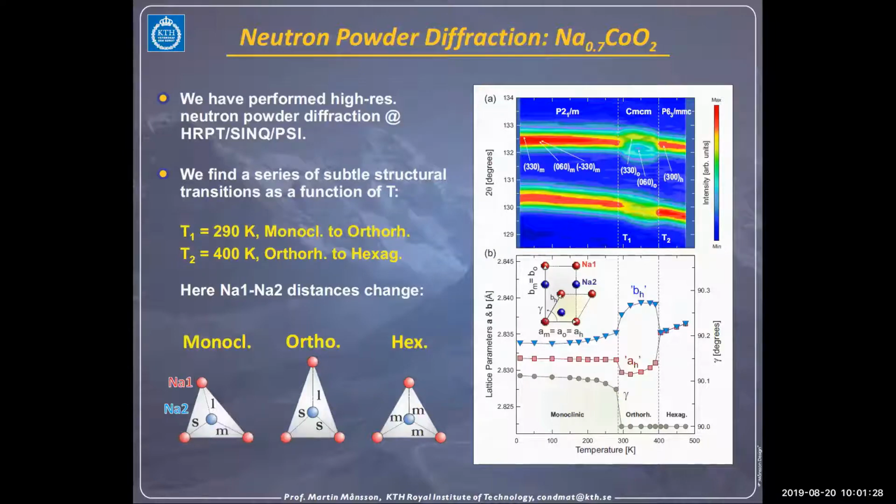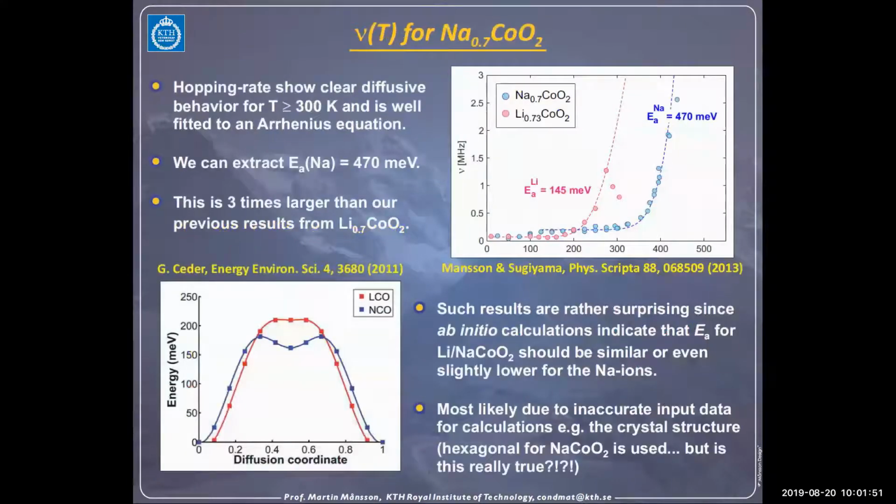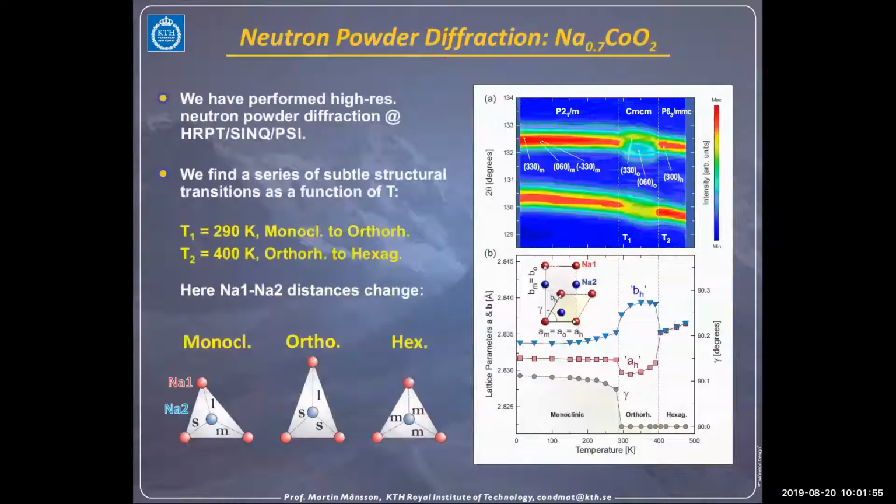These are 2 diffraction peaks. This is temperature along the x-axis. We see that 1 peak or 2 peaks splits and change around room temperature. And then the second one, it splits again and goes back somehow, emerges again around 400 Kelvin. So room temperature 300 or 290 and 400. Yet, of course, you see this 300 here. This is kind of also where this starts to happen. This is already kind of an indication that something is connected.